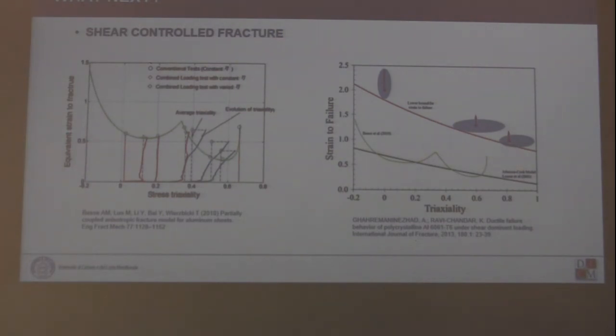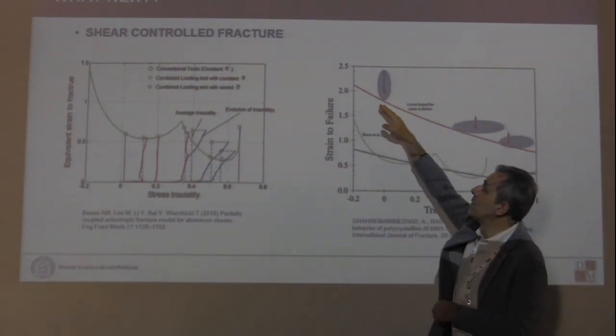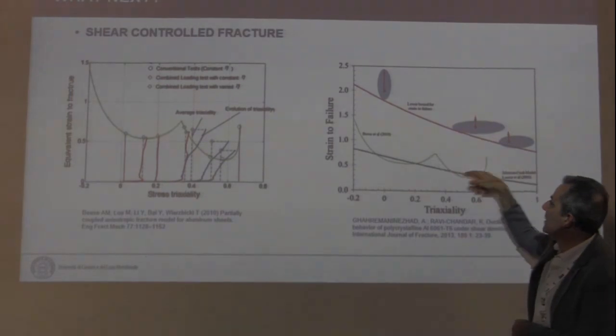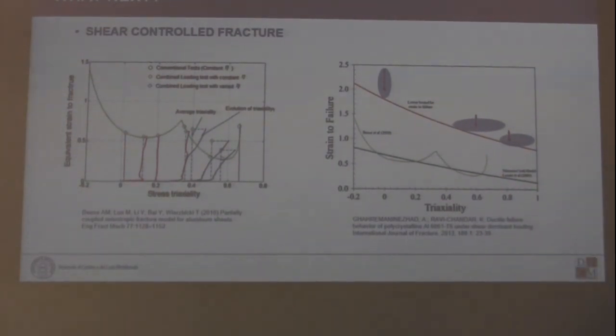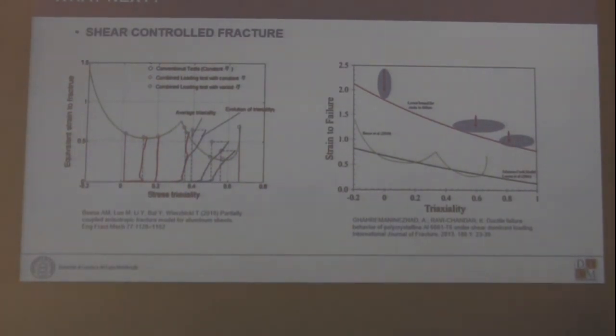Just recently, Ravichandran revised the experiments of Bao and Wierzbicki, and he proposed a much more detailed method to measure strain at failure using grain deformation in the fracture surface, and he found that the failure locus is probably here, while others measured this. So there is a lot of discussion ongoing on what is the real material behavior under shear. This is the part of the work that probably needs to be investigated more from the experimental point of view, in a very controlled way, in order to provide reliable data that can then be used to support modeling.